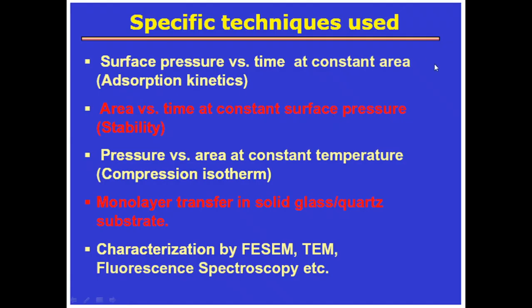During the preparation of the Langmuir monolayer, some special characterization techniques are used to observe its formation. This is the surface pressure versus time at constant area. This is called the adsorption kinetics, and area versus time at constant surface pressure, that is the stability. Once the Langmuir monolayer is formed, stability needs to be checked, and then surface pressure versus area at constant temperature. This is called the compression isotherm, and this is the most important thing that we have to check to get an idea about the preparation of two-dimensional crystalline films, Langmuir monolayers.